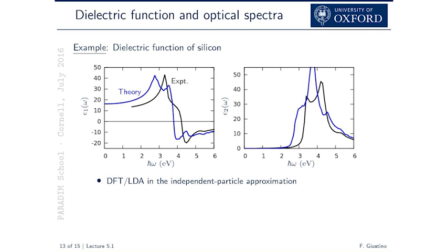In this case, in silicon, the gap is about 1.2 eV in experiment, and about 0.6 in calculations, in these DFT calculations, okay? But that's the indirect gap. What's relevant here is the direct gap in silicon, which is maybe 3.2 in experiment, and it's about 0.6 eV lower in theory. So actually, it's almost a rigid shift. In fact, you see that this is about maybe 0.6 eV lower.